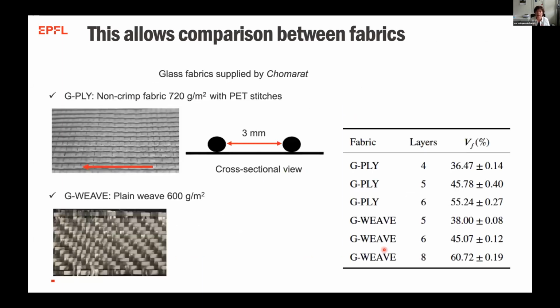We can also use this technique to compare different fabrics. This was another example where we compare two fabrics. One is the G-weave, a normal woven plain weave glass fabric. And this one was a fabric made by Chomarat, which is a non-crimp fabric made for having a super high permeability. You can barely see, but it has a lot of stitches, every 3 millimeters, with some kind of tow. And then you had the bottom, which was the UD tow. So it's a kind of long UD, but with a lot of cross tows that are quite thick here. That makes really big channels in between.